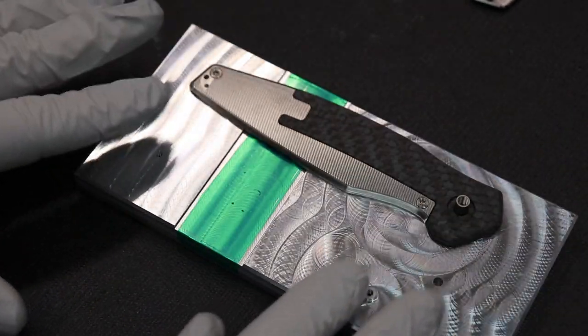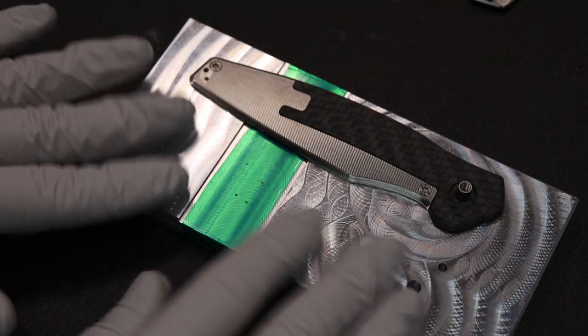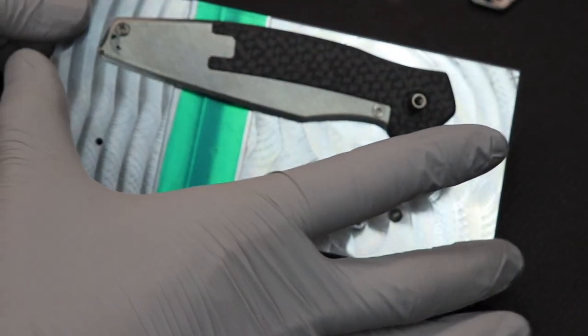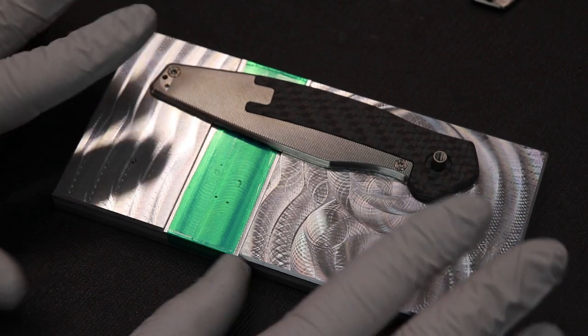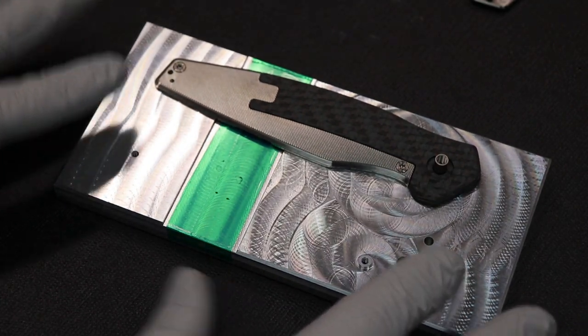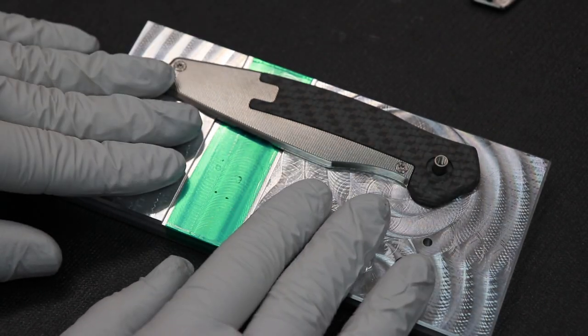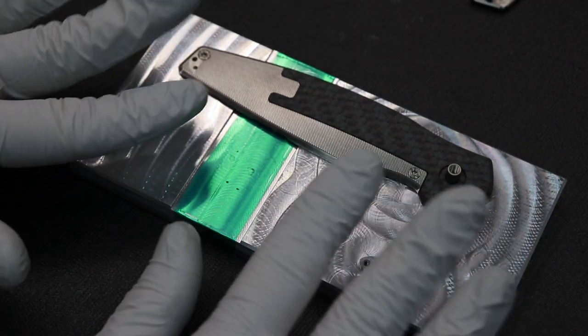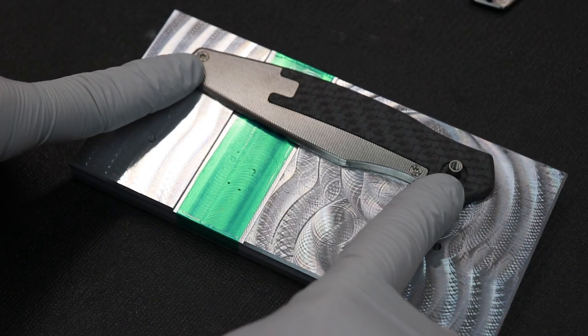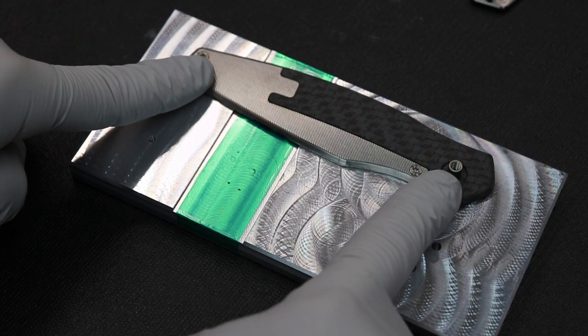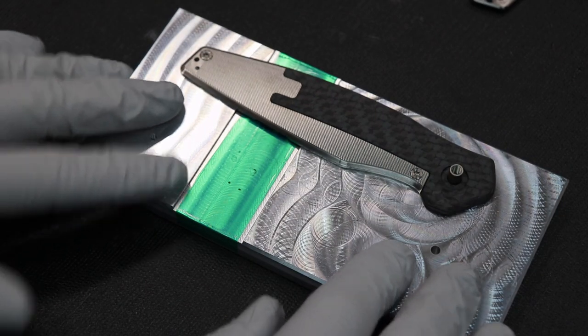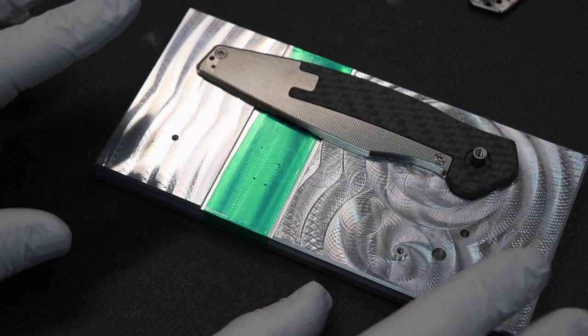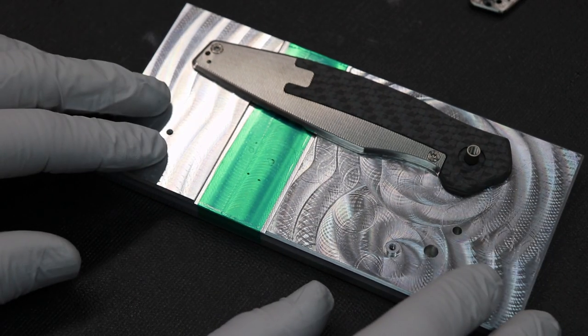The big problem with this fixture is that it's aluminum. And aluminum is subject to a lot of thermal expansion. So this width right here and this width here, they need to stay constant during the cure cycle. So this fixture I can only do at room temperature, and really it needs to stay at pretty much the same temperature that it was machined at, which is around 70 degrees or so. If I put it in the oven at 180 degrees, this position from here to here would change dramatically. Like if you cured it in that state and then took it off and then let this cool down, it would not fit back on. This works for now, it just takes a little time. And the resin that I'm using takes about 24 hours to cure.